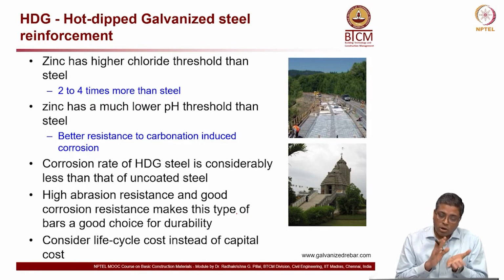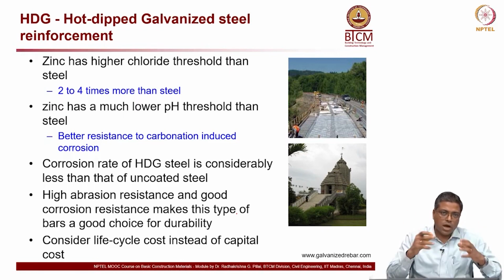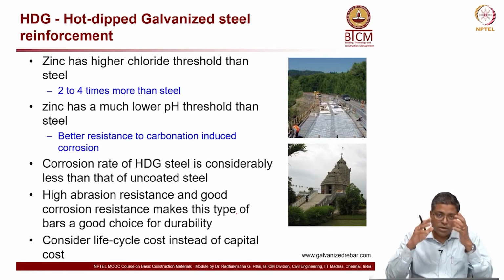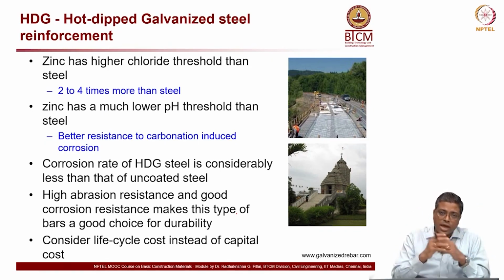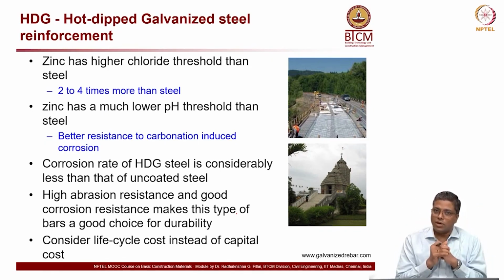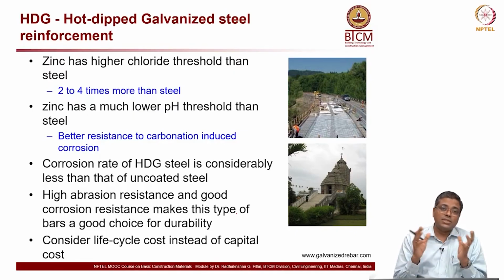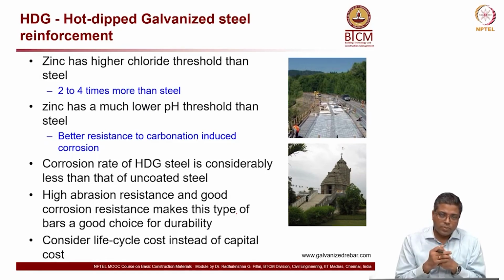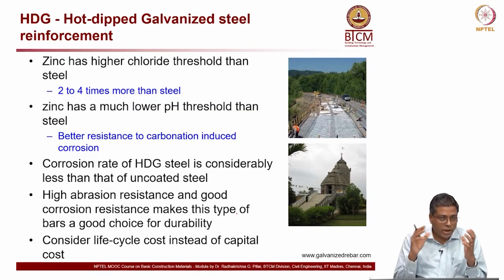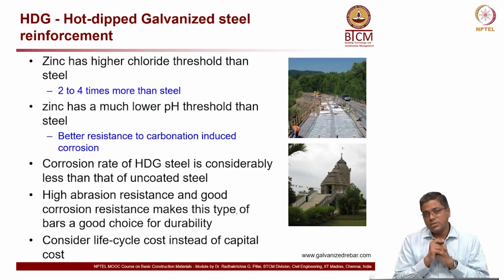Now, when you talk about carbonation induced corrosion, again there is a pH threshold. The concrete gets exposed to carbon dioxide and chlorides, and the carbon dioxide reacts with the concrete, and then the pH of the concrete will decrease. When the pH of the concrete decreases, the steel inside can start corroding. When you put this galvanized coating, the amount of pH reduction it can tolerate is also significantly high. So you again have very good protection against carbonation.